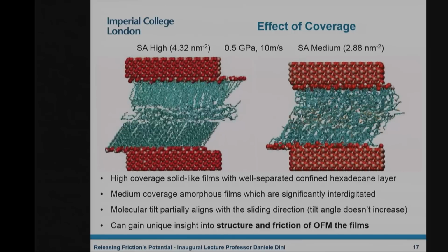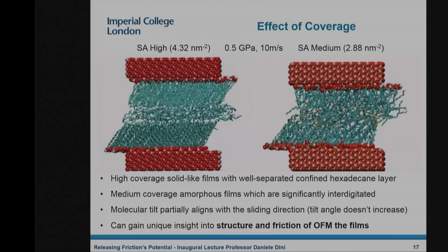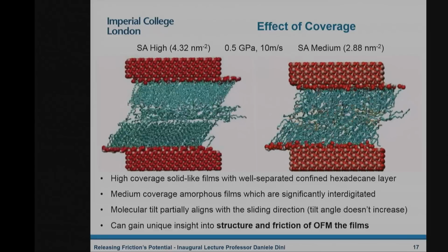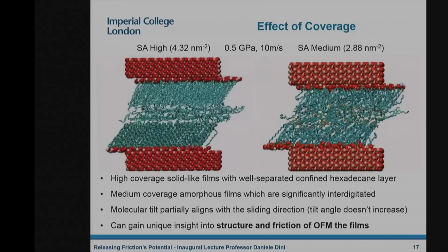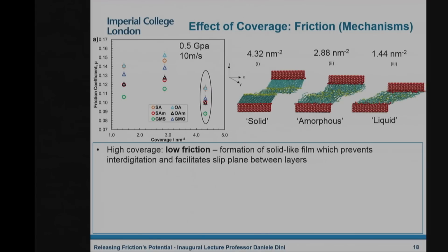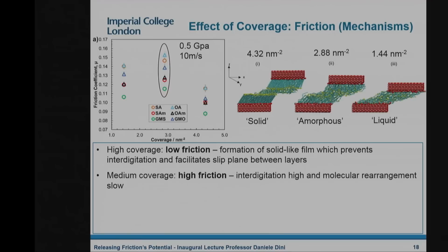And it's a bit like looking at nice al dente spaghetti here and badly cooked spaghetti over there. You expect the badly cooked spaghetti to be much gluier and giving higher friction. And it's actually exactly what happens. You look at this system and you see that if you look at the maximum absorption, so if you put a lot of these polymers on the surface, or if you decrease the quantity, you have different kind of effects in terms of shearing of this lubricant. And in fact, what happens is that the lowest friction happens when you have a lot of those. So you create a very structured system, and the slip is confined between the two layers of brushes. Whilst if you go down in terms of coverage of the surface, you start getting this intermingling between the molecules that stops you from doing easy movement between the surfaces.